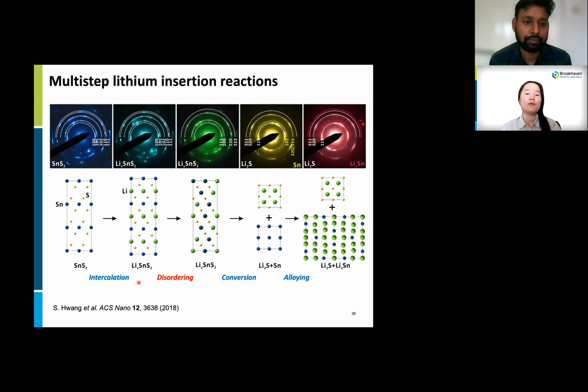From the snapshots of electron diffraction pattern videos, I can clarify 4 steps of the lithiation reaction. At first, lithium is inserted into the empty space between sulfur layers, so intercalation happens. Then when further lithium is inserted into this compound, lithium and tin disordering happens. Originally it has a layered structure, but it becomes a rock salt-like disordered structure. Then with further lithiation, the conversion reaction happens. So lithium tin sulfide is converted into lithium sulfide and tin metal. And eventually this tin metal can make alloys with lithium.